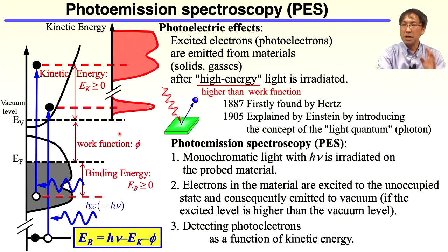The photoemission process is of course a one-photon process following Fermi's golden rule, which means that we can use the energy conservation law. When we define the binding energy EB from the Fermi level located here, we can get the binding energy by measuring the photoelectron kinetic energy, where the energy conservation law is expressed like this.